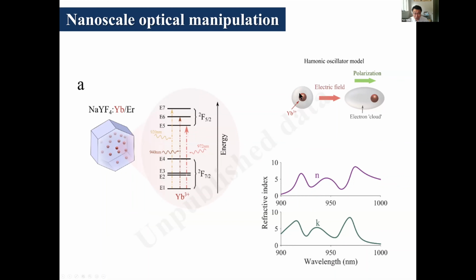So what we're seeing here is actually the ion resonance. This is really, really interesting. Basically, if you have the electric field, you push the ions, the electron cloud, into another position, so it's kind of just a polarization. But in this material we have multiple Stark levels, which really helps, because if you look at the permittivity, or the susceptibility, all the dips are balanced with the peaks. Because of limited time, I won't go through the detail. But this, combined with the Stark levels, gives you really high refractive index if you match the resonant condition but are off a little bit from the scattering condition.